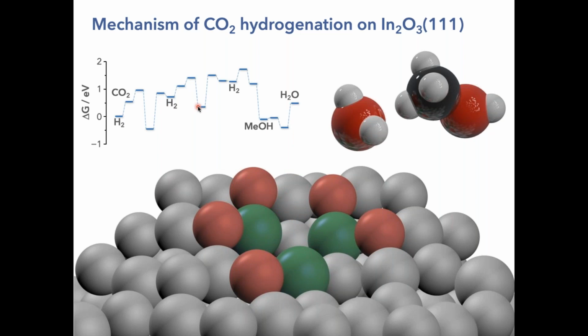The reason I put the energy profile here is twofold. First of all, I want to show why this catalyst is selective to methanol and not to CO, which would be the reverse water gas shift. And that's because the reverse water gas shift reaction has a much higher energy intermediate, which leads to the system going the blue pathway, going to methanol. And the second reason why I put this is because although the material is extremely selective, one of the problems of using indium oxide as well as other oxides, like for example zinc oxide, is the very difficult activation of hydrogen on these systems, rendering them less active compared to copper-based systems.